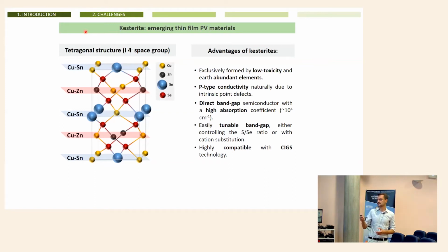In addition, the material is exclusively formed by low toxicity and earth abundant elements, and exhibits naturally p-type conductivity that is quite easy to control. Also, most of the different alloys exhibit direct band gap, and in the region that is of interest for photovoltaic application, between 0.8, 0.9, up to 2 electron volts if you want, or even more.